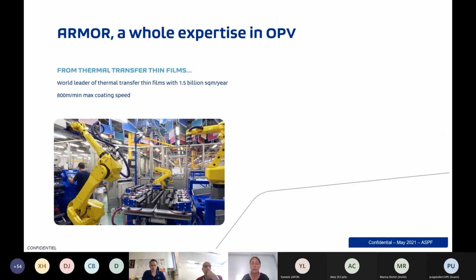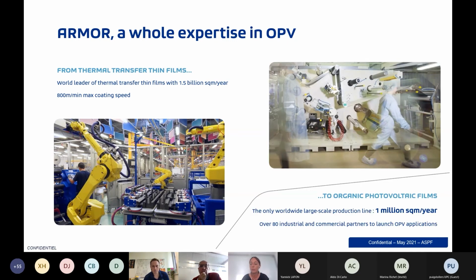So why OPV for such a company? For the thermal transfer film, we are coating in a wall-to-wall at really high speed, till 800 meters per minute speed. And our expertise is in formulation and coating. So we keep this expertise in formulation and coating to develop some organic photovoltaic film in the same schema. Meaning that we already have installed in Nantes, in France, a large-scale production line for OPV that has a global capacity of 1 million square meters per year for OPV films.